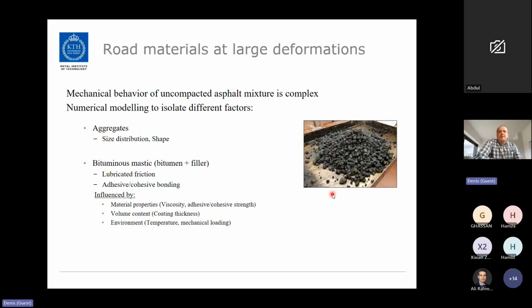But also bituminous mastic, the binder phase, mixture of bitumen and fine particles, affects the response quite a bit through two main mechanisms. Bituminous mastic lubricates frictional contacts and improves flowability, but at the same time it provides adhesive and cohesive bonds between particles, which means that it can also decrease flowability of asphalt mixture. And those bituminous mastic properties are in turn significantly affected by a bunch of material properties: viscosity, adhesive and cohesive strength, the amount of binder available, coating thickness, and environmental properties in terms of temperature and mechanical loading.